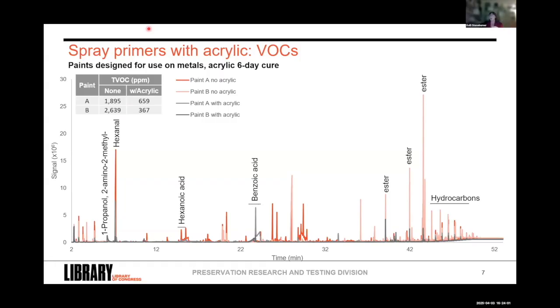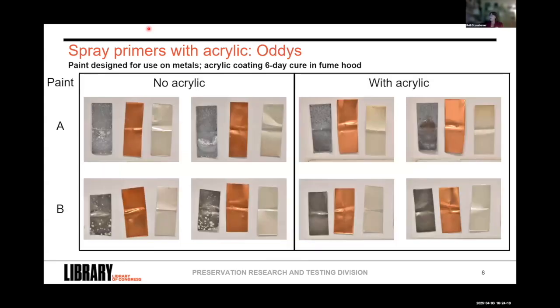We were still seeing some carboxylic acids with the top coating on them, but significantly reduced in the number of them and their overall concentration. So it's not perfect, but this is looking a lot more promising than we had been seeing previously. And then when our Oddy test came out, paint B especially here was very exciting, as our lead coupon went from an unsuitable rating to a pass. And silver looked good. There was, I think, one coupon had a slight hint of lightening, so it got an overall temporary rating.